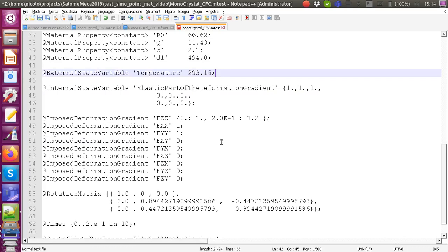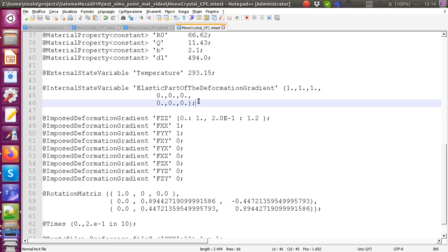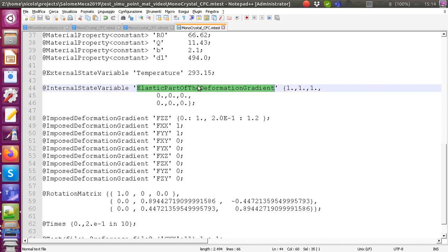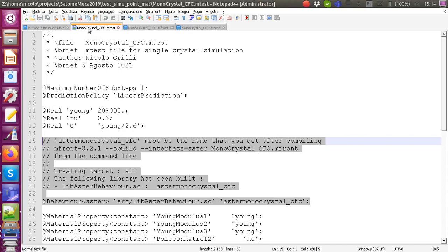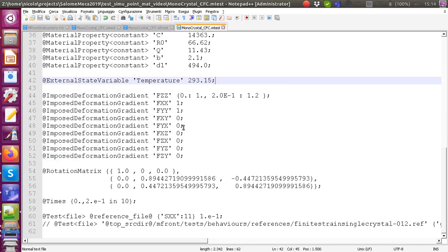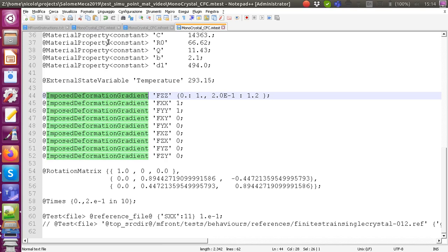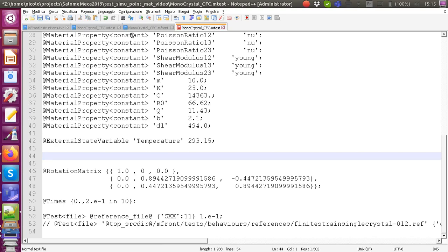Because this mTest template is similar but not exactly the same as what's needed for this material model, the elastic part of the deformation gradient does not exist in this particular mFront model. So you simply remove that internal state variable. Other modifications are related to the boundary conditions: in the original file there is an imposed deformation gradient, but the monocrystal_cfc model is a small strain model, so those must be cancelled and replaced with small strain boundary conditions.